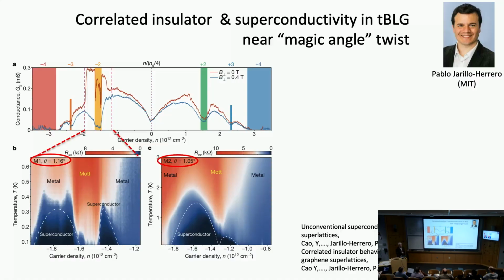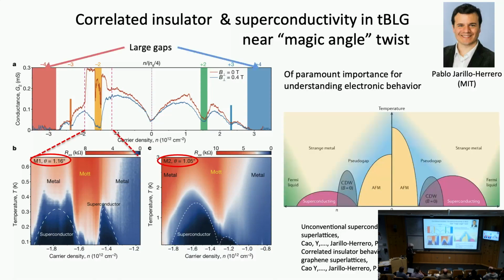And the color coding here is the behavior of the system. This is for two different angles, 1.16 degrees twist between the two layers of graphene, or 1.05 degrees twist. And as a function of temperature, you see superconducting behavior in this range of temperature and doping. Also superconducting over here. In this range, it's an insulator, a Mott insulator. Over here, it's a metal, and over here, it's also a metal, and so on. And the behavior in this slightly different twist angle is very similar. Why am I going through all this? Because there's a striking resemblance of this phase diagram of the different phases that the system undergoes as a function of doping and temperature to high temperature superconductors.